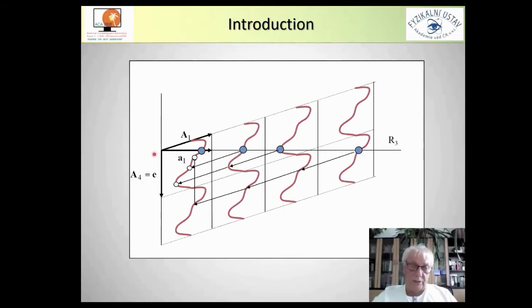With this we can see that this curve in the first cell describes all possibilities of positions of atoms, which are produced by a section perpendicular to this e vector. So the real structure, as derived from this artificial description in direct space, is produced by a section of this periodic density in two-dimensional artificial space. But we can also move this line a little bit down, and we can see another situation in the crystal, which means that we can make different structures by different sampling with different sections. If this modulation vector is really incommensurate, all these sections are equivalent.